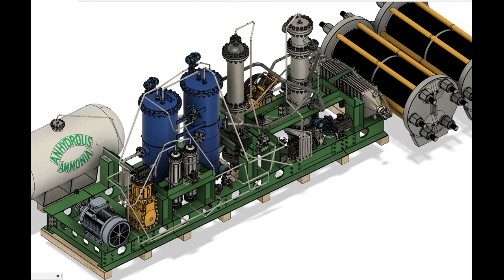Early ammonia synthesis catalysts were based on magnetite, reduced with hydrogen after melting with alkali promoters to produce the desired iron crystal structure. The new generation of iron catalyst, while nearly identical in overall form, made use of the slightly different wustite crystal structure. What's remarkable is the ammonia synthesis catalyst is considered the most durable catalyst among all industrial catalysts, showing virtually no structural and morphological changes after 20 years of extreme conditions of pressure and temperature.